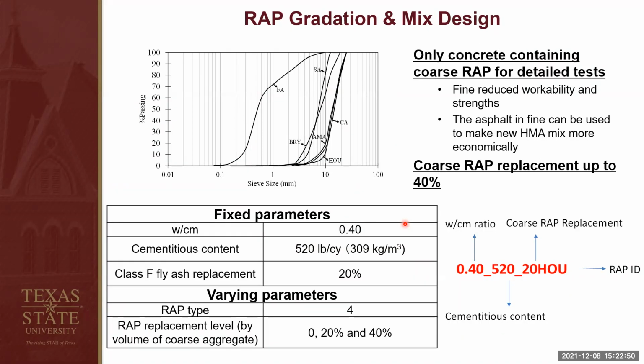On this slide, I'm showing the gradation of the RAP and also the mix design we did. As you can see, as I also mentioned in the previous slide, we have Houston, Amarillo. Those RAPs contain a lot of large-sized aggregates, and their gradation was very similar to the gradation of the virgin coarse aggregate we used in our concrete.